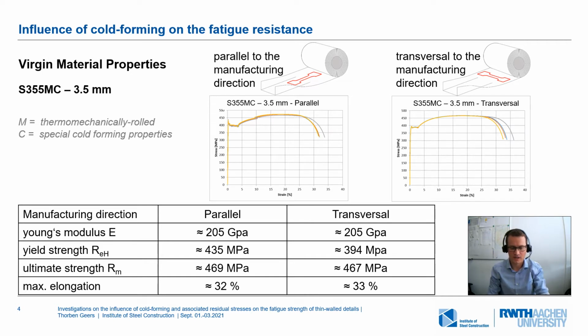There is only a small difference in the yield strength, which is 435 megapascal parallel to the manufacturing direction, and we have a lower value of 394 megapascal transversal to this direction. This difference is to be explained by the manufacturing process of the mother coil, but this difference doesn't matter that much.